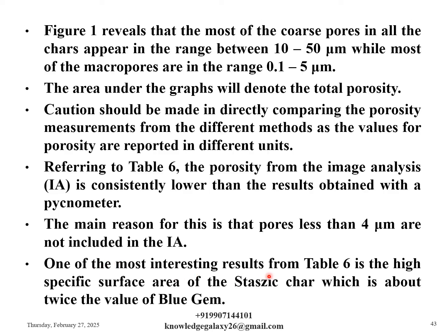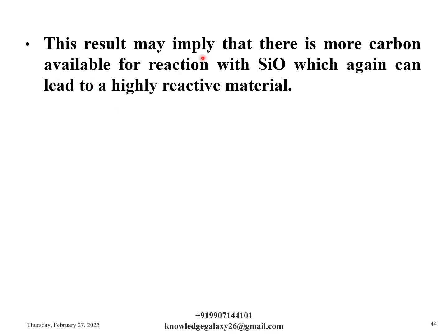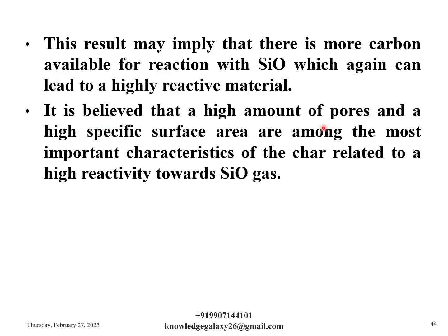One of the most interesting results from table 6 is the high specific surface area of the Staszic char, which is about twice the value of blue gem. This result may imply that there is more carbon available for reaction with SiO, which again can lead to a highly reactive material. It is believed that a high amount of pores and a high specific surface area are among the most important characteristics of the char related to a high reactivity towards SiO gas.